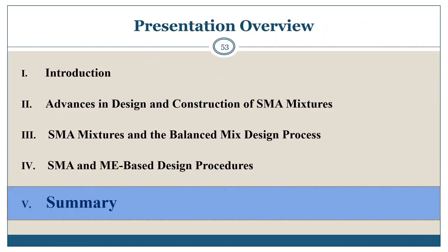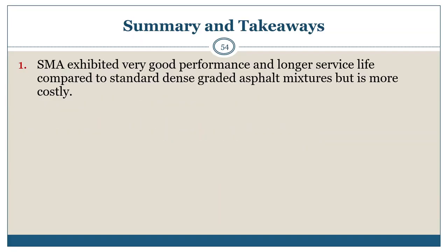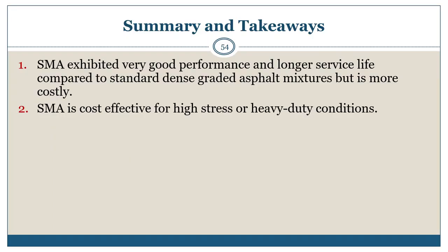So in summary, this is section 5, a summary of the takeaways in terms of the final discussion. SMA mixes exhibited very good performance and longer service life compared to standard dense graded asphalt mixes, but it is more costly. Many studies have shown that SMA mixes have significantly longer service lives. SMA is, however, cost effective, even with the higher initial cost, for high stress and heavy duty conditions. The reason for the cost effectiveness is the longer service life, even though the initial cost of the mix is higher.